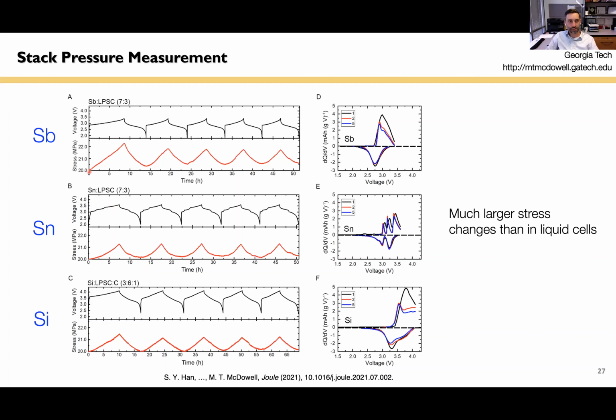And then when we charge, you can see that the stack pressure increases. And then when we discharge, it decreases, and then it's cyclic from there. Increase, decrease, increase, decrease, increase, decrease, etc. And so that's the same for all these materials, but some of the details are quite different.